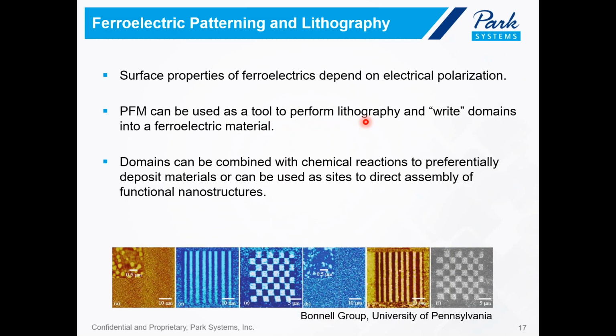A little bit about ferroelectric patterning and lithography, as we are going to highlight the ability for PFM to do lithography with the sample. So the surface property of a ferroelectric material depends on the direction of the electric polarization. And domains of the material will essentially be chosen, and you can write into the material to have a desired electrical polarization or desired surface property. So PFM can be used as a tool for ferroelectric lithography to write domains with nanoscale precision without affecting the surface topography. And these domains are then often used to perform subsequent chemical reactions or can provide sites for controlled assembly of functional nanostructures.